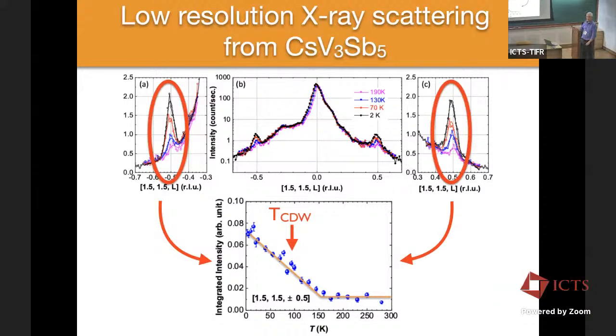And the 94 Kelvin anomaly associated with the charge density wave, which, as I mentioned, is very reproducible from sample to sample, and it's reproducible in our samples, is almost the midway point on the order parameter, and it extends up to much higher temperatures, something more like 150 Kelvin. So the way we interpret this is that, at low temperatures, we're seeing the long-range order associated with the charge density wave state, but at high temperatures, we're seeing the fluctuations associated with the charge density wave state above the phase transition, and actually we can see them go up to very high temperatures, right?